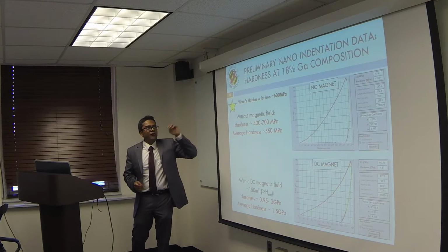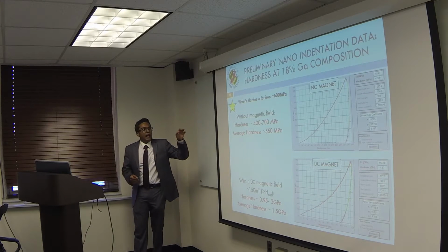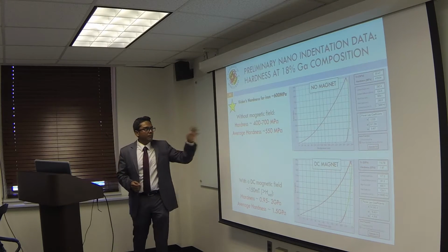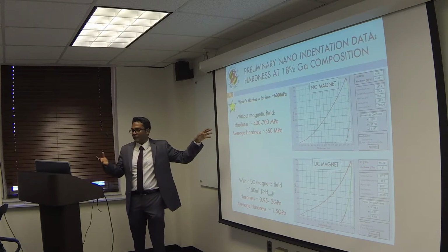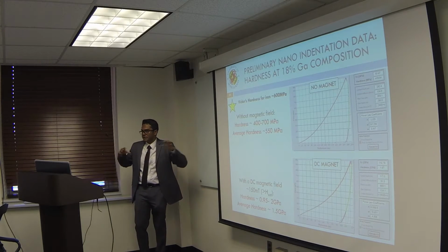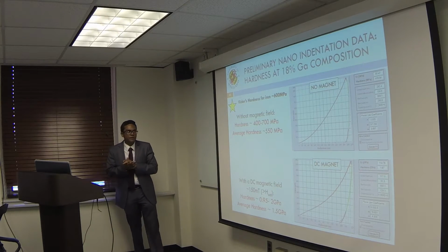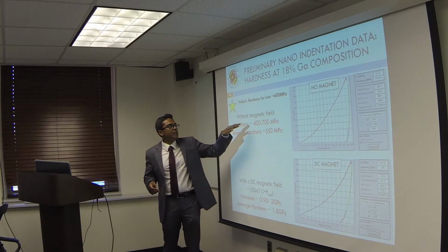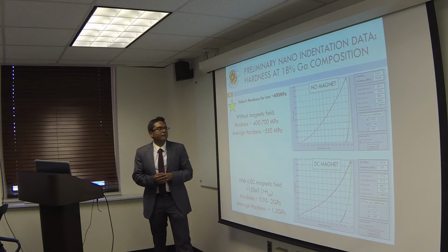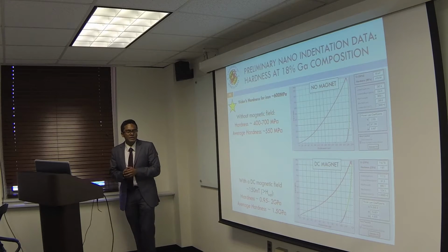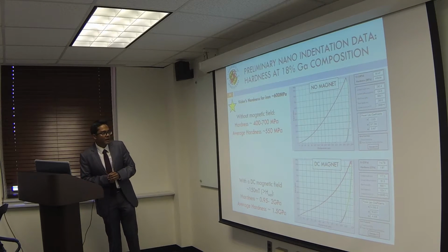So the Vickers hardness for iron is 600 megapascals. And the value of hardness for Galfenol has to be slightly lower because it's a softer alloy, because gallium is softer than iron. And we found that the value without a magnetic field is between 400 and 700 megapascals, and the average was around 550 megapascals.